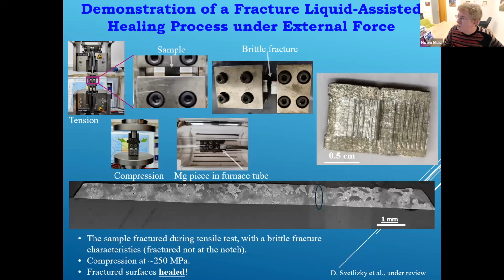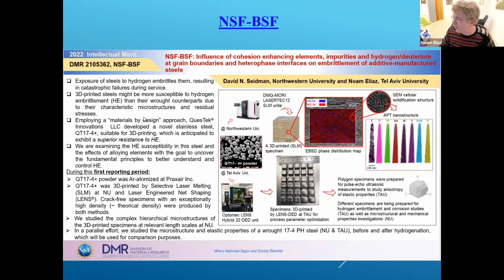And just to show you what you can see here, this is the magnesium part. We made a total fracture, and this is the same part on the right-hand side after we did the compression in that atmosphere. And this is the macroscopic view of the cross-section, just to show you where you see the ellipse. That's where the original fracture was. So it's still, of course, not perfect, but at least it encourages us that there is feasibility.